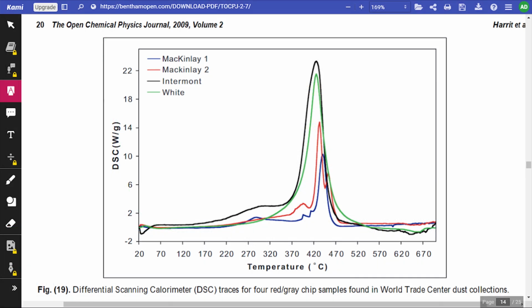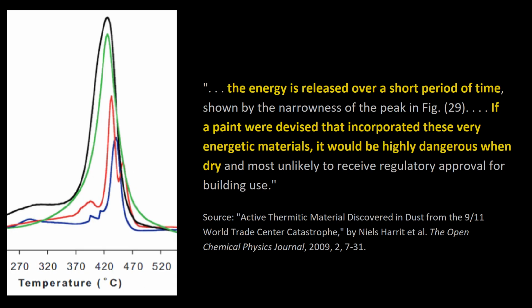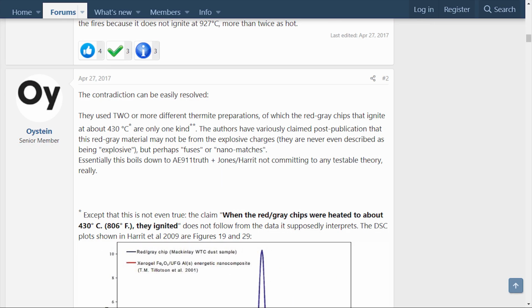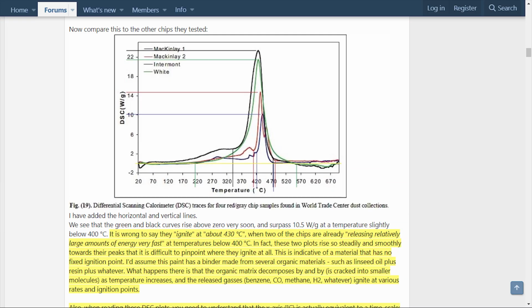It may look impressive on the graph, and they certainly do a good job of selling it using all kinds of dramatic language, but Oystein of Debunked.org explains it in such a way that it takes a lot of the wind out of their sails. Quote, "It is wrong to say they ignite at about 430 C, when two of the chips are already releasing relatively large amounts of energy very fast, at temperatures below 400 C. In fact, these two plots rise so steadily and smoothly towards their peaks that it is difficult to pinpoint where they ignite at all. This is indicative of a material that has no fixed ignition points.